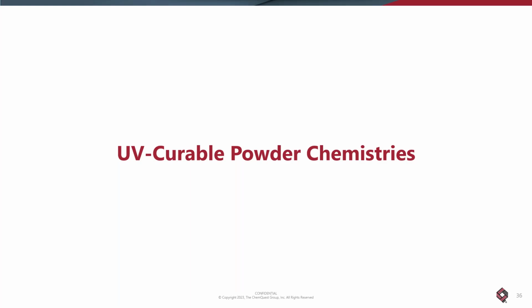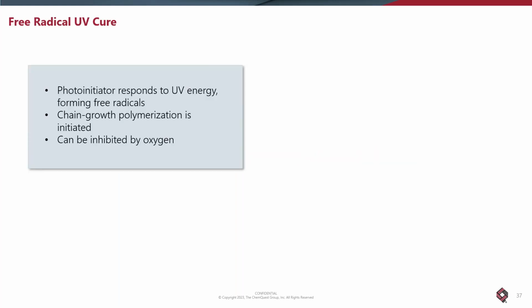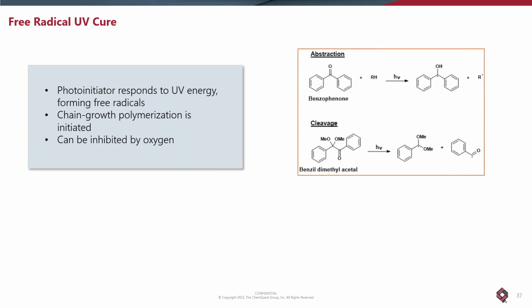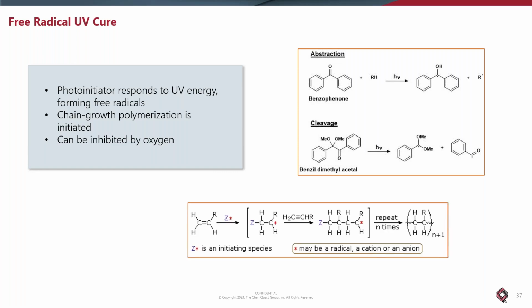Powder chemistries, and I'm only going to talk about free radicals. There is a subset of cationic cure. That's for another discussion. We could do that offline. But basically, a photoinitiator gets things rolling after you've melted and formed a film of the powder. And you get your chain growth polymerization of your free radical groups. And there's a possibility of oxygen inhibition, although for some reason the polymers and the systems used in powder coatings don't seem to have much of a problem. And I'm not exactly sure why.